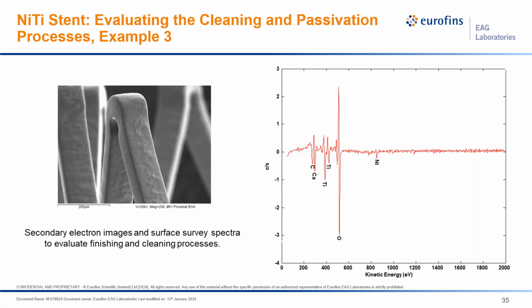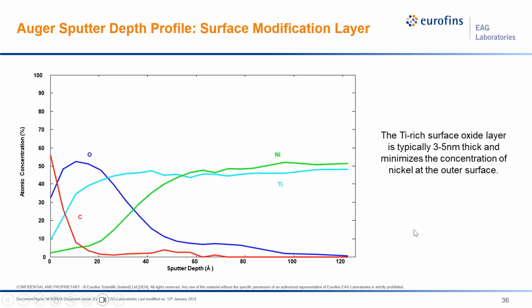Reducing the concentration of nickel at the surface is extremely important, for some people have nickel sensitivities. And when these things are implanted, it's very critical that surface chemistry is controlled well. Sputter depth profiling, we can actually verify that we have a nice passivation layer here where there's titanium-rich oxide, a little bit of carbon, adventitious carbon probably just from exposure in the ambient lab, and then the nickel-titanium substrate. Very typical sputter depth profile there.